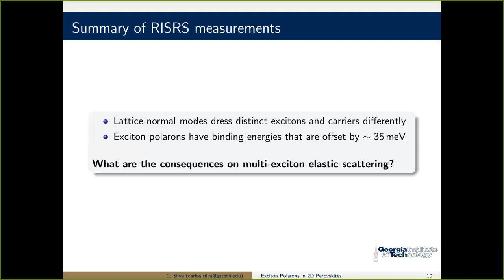And it is still a reasonable hypothesis to say that these are exciton polarons with binding energies that are offset by 35 milli-electron volts. And so that is the message from these time-domain vibrational spectroscopies. So we see the distinctness of the excitons. But okay, we may have exciton polarons, and that's useful to know.